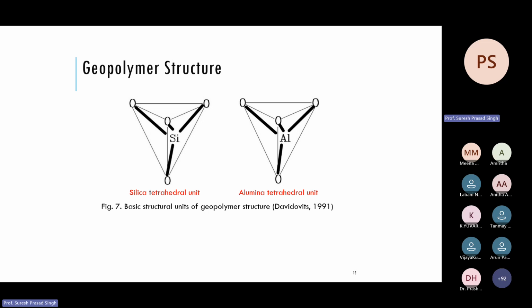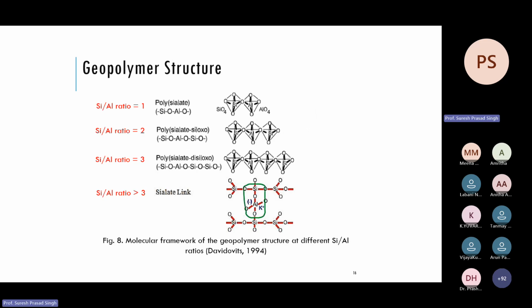So next, this is linked to form a chain-like structure or continuous structure. We have this depending upon the silica alumina ratio in our aqueous solution. If it is close to 1, we call it a polysialate. If it is 2, we call it polysialate siloxo. If the silicon to alumina ratio is 3, we call it a polysialate disiloxo. Here a sialate ring like this one. So next you see how it is linked.